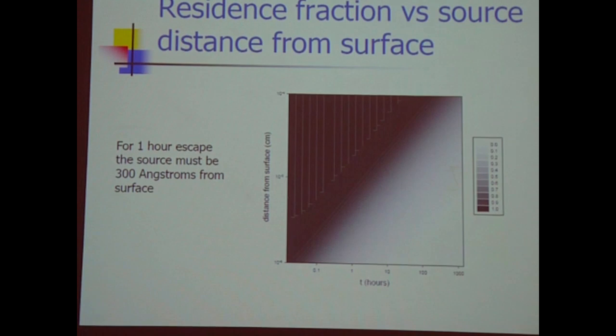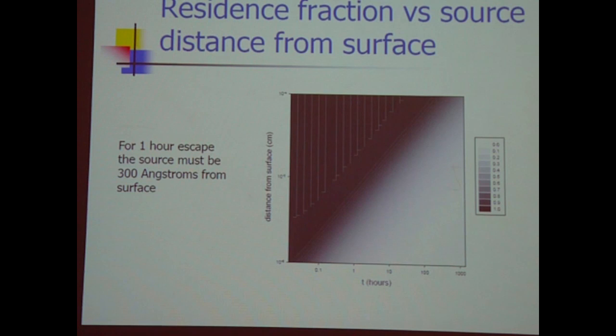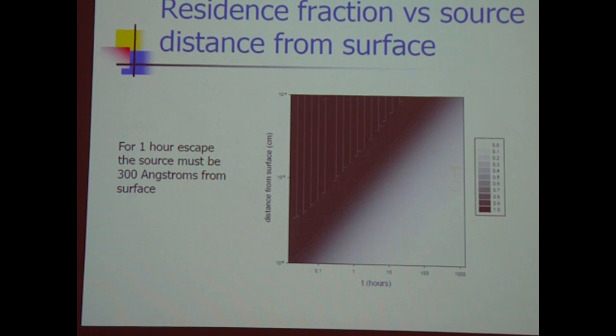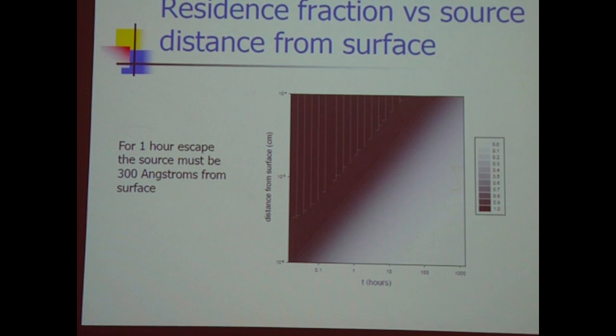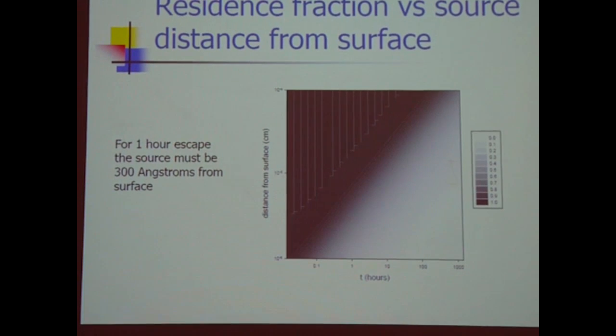So, I'm sorry, 10^-6, 10^-5, 10^-4. So on the order of 1,000 angstroms from the surface would be consistent with the helium-4 going into gas phase measurements. And this is interesting because it is consistent with this co-deposition picture: to get the vacancies, you've got to have the high loading above 0.95, you co-deposit on the surface. Well, how much do you co-deposit? In the Fleischmann and Pons experiment, you co-deposit 1,000 or a couple thousand angstroms of material. So this seems to be a plausible explanation as to why you would see temperature dependence in excess heat experiments.